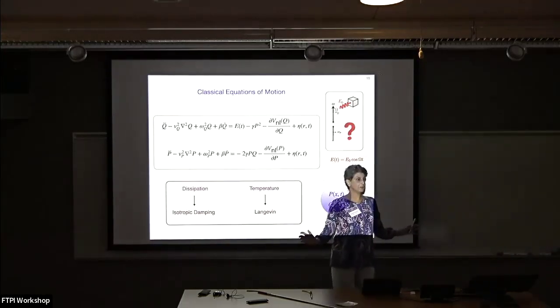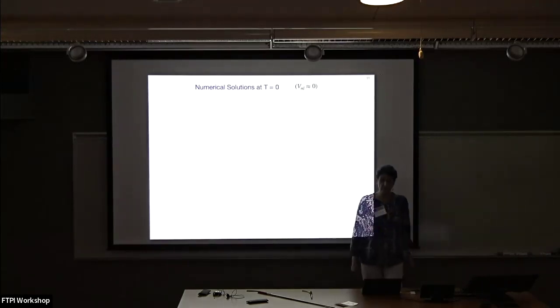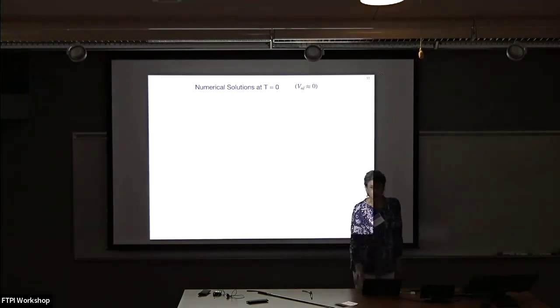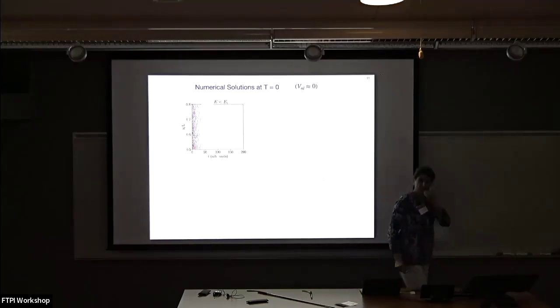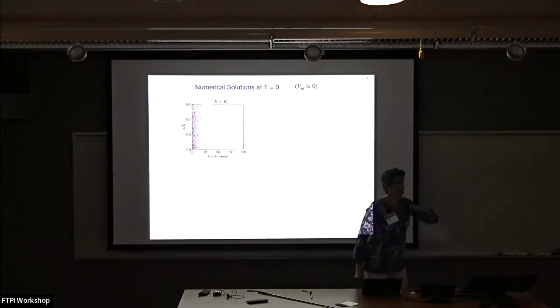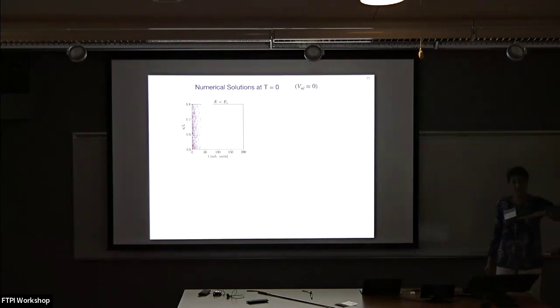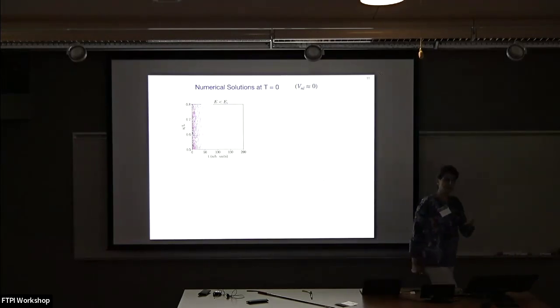Let's first do this numerically. So let's look at numerical solutions where T equals 0, and we're going to assume that those self-interaction nonlinear terms are effectively 0. They have to be very small just to make sure that we can have regular solutions. So what Daniel has done is he's taken our initial P's and Q's from a uniform distribution with 0 initial velocity. He's done the calculations using the standard Langevin techniques. And he assures me that because of the structure of his solutions and his equations, they satisfy a criterion which tells us that the integration is stable.